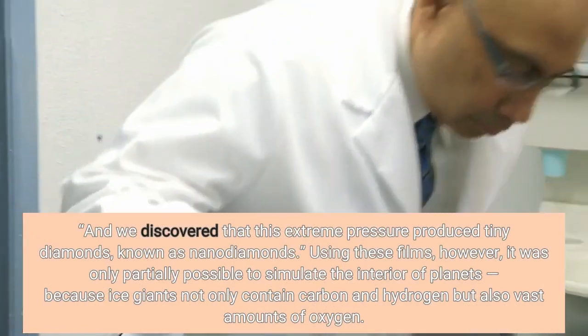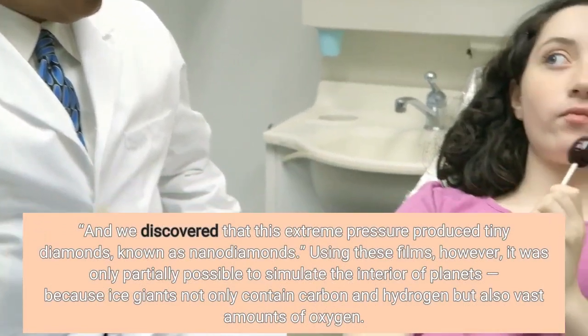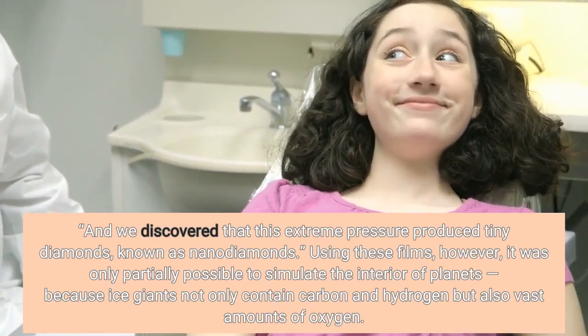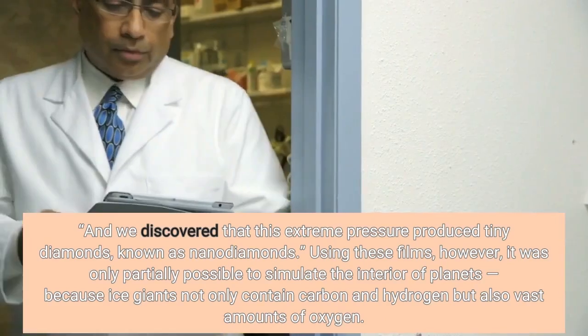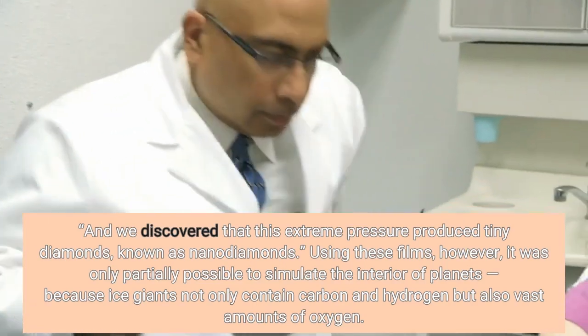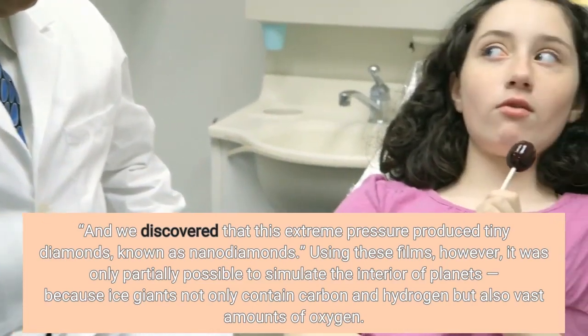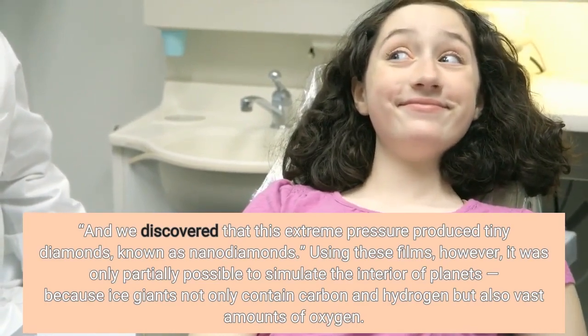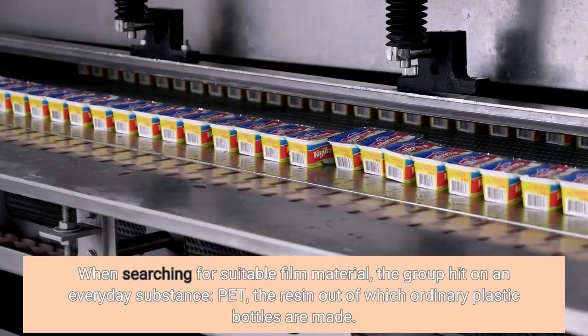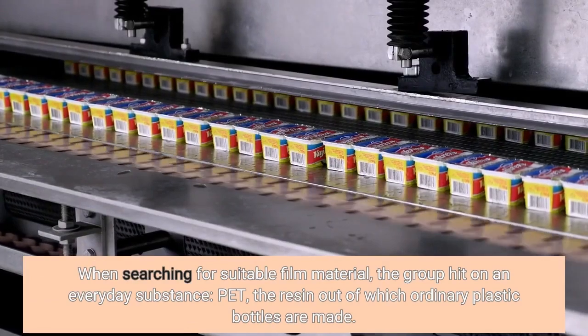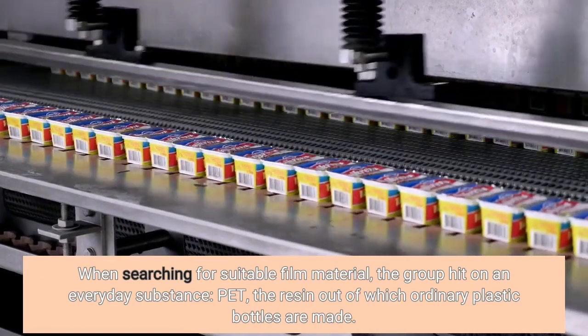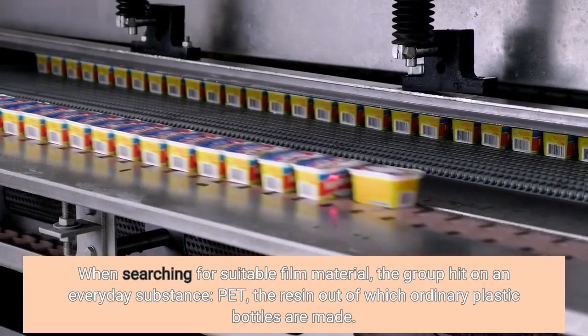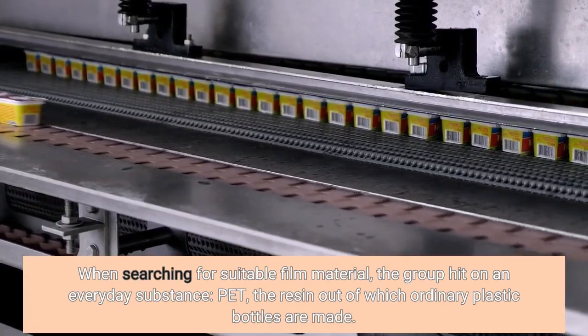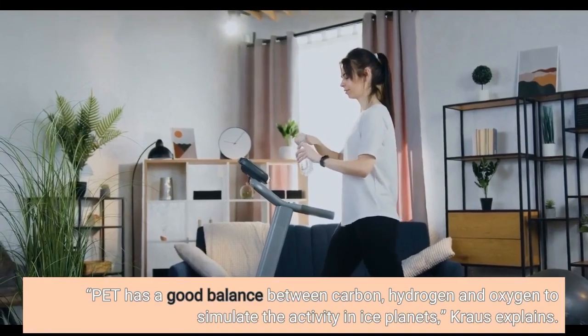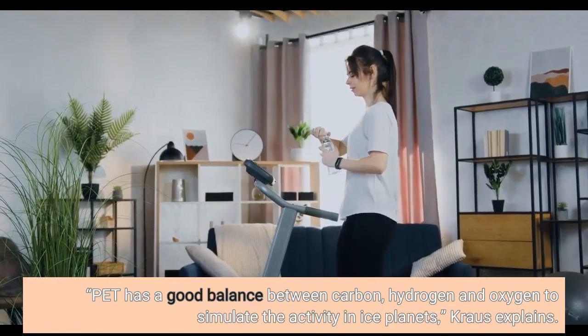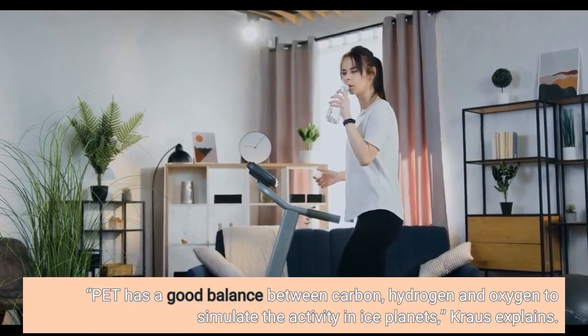And we discovered that this extreme pressure produced tiny diamonds, known as nanodiamonds. Using these films, however, it was only partially possible to simulate the interior of planets, because ice giants not only contain carbon and hydrogen but also vast amounts of oxygen. When searching for suitable film material, the group hit on an everyday substance, PET, the resin out of which ordinary plastic bottles are made. PET has a good balance between carbon, hydrogen and oxygen to simulate the activity in ice planets, Kraus explains.